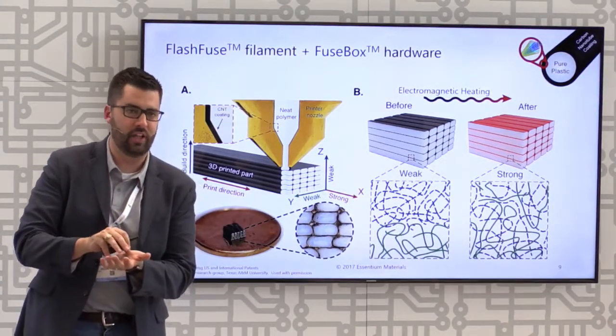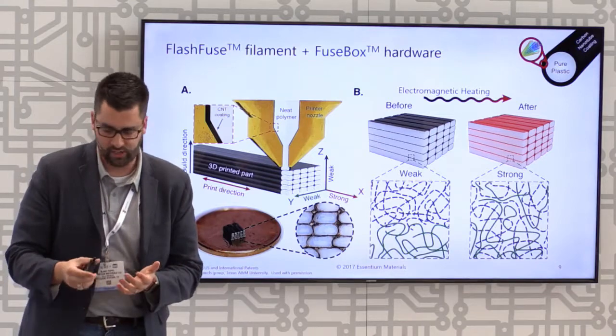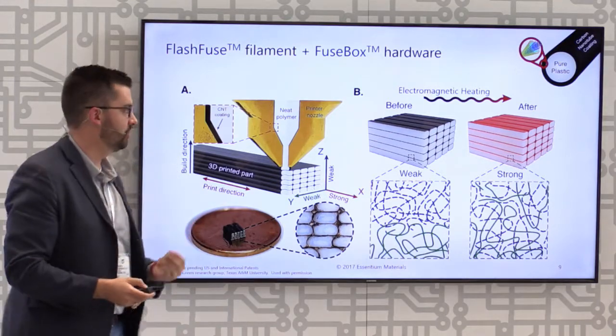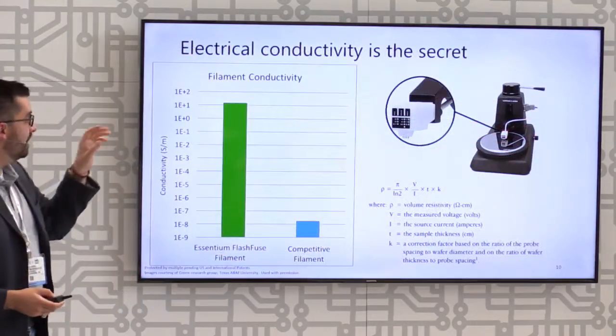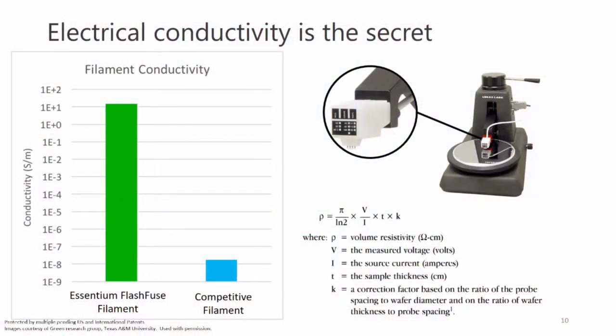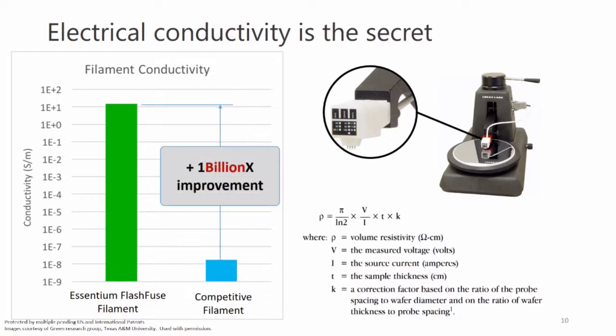This promotes interlayer strength, dramatically increasing the whole part isotropic properties. And here's the secret sauce. This is why this works. This is why this is special. Because our electrical conductivity is 1 billion times higher than the next closest commercially available electrically conductive filament.